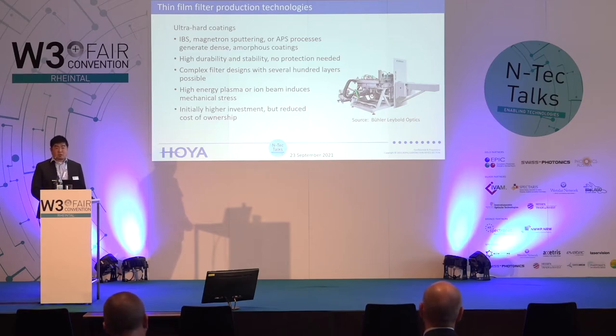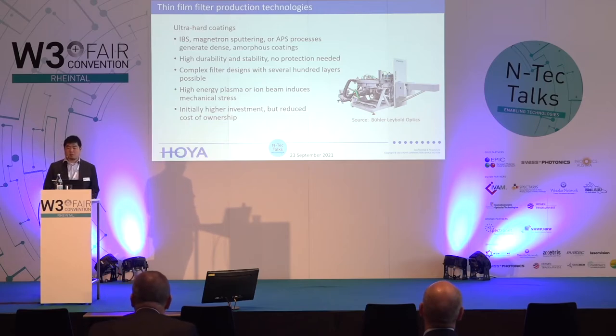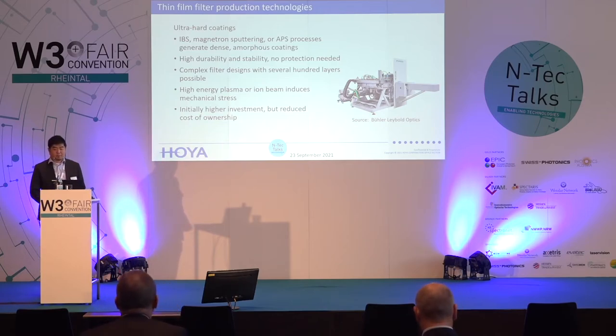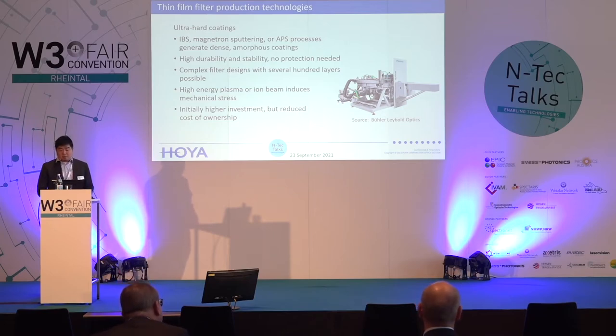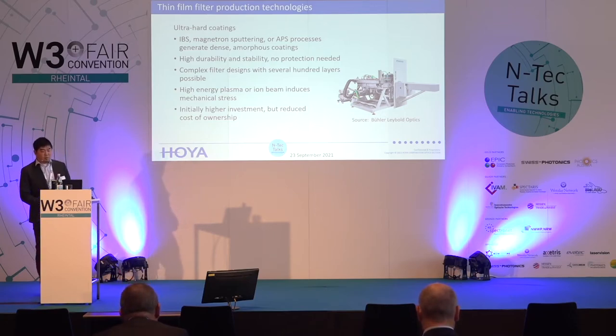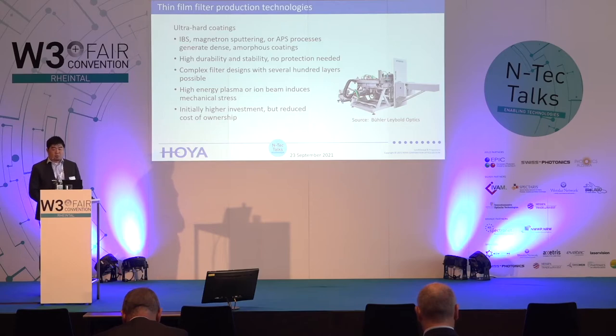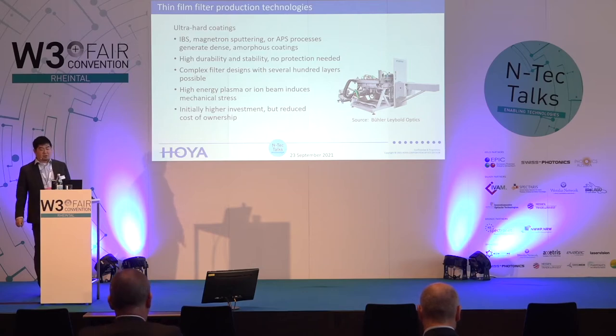So we have recently seen advanced filters with 300 layers on each side, which was not possible just several years ago. But that comes, of course, at a cost. The high-energy plasma or ion beam induces mechanical stress in the coating, which leads to bending of the substrate. The thinner the substrate becomes, the more severe the bending is.